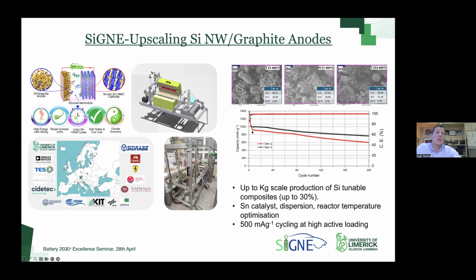So you'd see two different generations of materials. We have our generation 3, which is 30% silicon content, and our generation 2, which has about 25%. And the idea here, this is just showing the kind of fast cycling test, is just to verify that you have this dual active composite where you have silicon and graphite, both of which contribute to your capacity. Again, significantly boosting it beyond what pure graphite can give us.